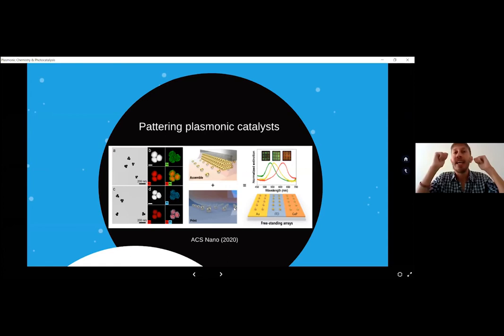Because most of the light has already been absorbed or scattered by the first layers of colloids. So then an idea is to place those colloids that have been designed for plasmonic catalysis in 2D, right? So to create surfaces where we can pattern these colloids in order to have maximum light excitation of the nanoparticles and also exposed surface of these catalysts. And for that, we have designed different methods to pattern these kinds of colloids on different types of substrates, right? So conductive substrates to perform photoelectrochemistry, or different conductive substrates or dielectrics.